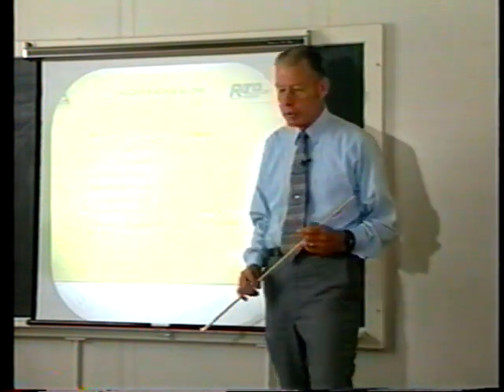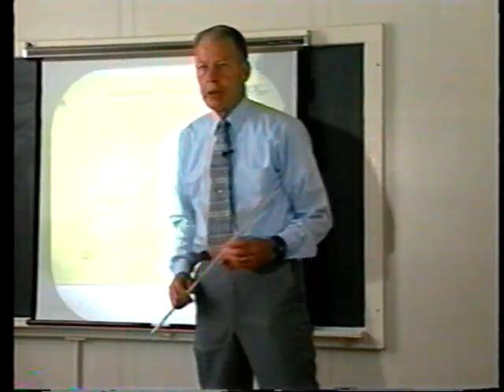X-ray diffraction showed that these materials were all two-phase materials. They had two distinct phases of the same cubic structure. Our first experiment on a palladium-boron alloy produced excess heat. This is the experiment shown here.